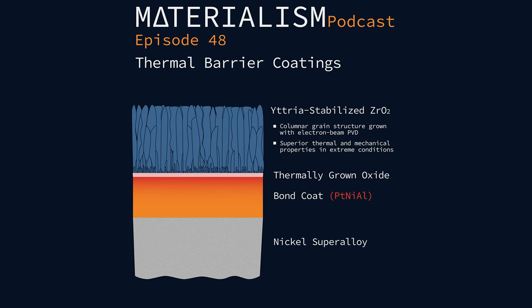So people have actually proposed maybe we could do that in our thermal barrier coatings. You could have YSZ and alumina alternating layers. And if you can control the thickness carefully, you could actually get reflectance to block some of this radiation, which would buy you even higher temperature operation. The problem, though, is that for this to work, they have to be very flat. The roughness needs to be less than 5 nanometers in one paper I saw. And they don't achieve that with EBPVD or plasma spray. So I don't know if this is not feasible or if it's just not something that somebody's tried or taken seriously yet. But it would technically be one way to prevent radiative heat transfer and therefore operate at slightly higher temperatures.